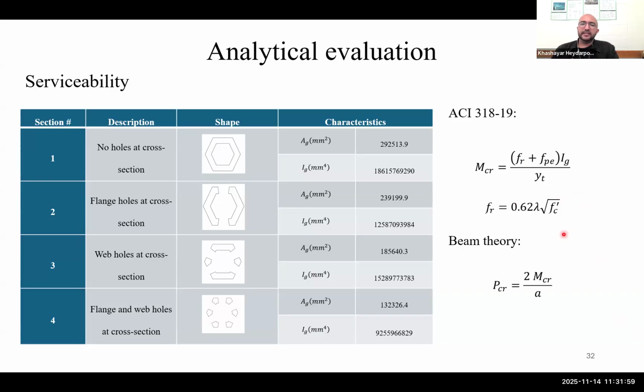In this equation, we can see that Fr is the modulus of rupture of concrete, and it is obtained from this formulation. And lambda equals 1 when we don't have a lightweight concrete. And the cracking moment can be obtained also from the modulus of rupture and also the concrete stress due to the precompression, fpe. And using the beam theory, we can get to the formula that the cracking load is 2 times the cracking moment over the shear arm of the specimen. That was 1,224 millimeters.